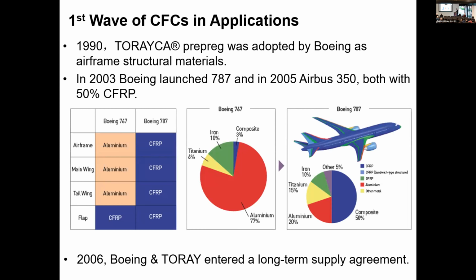If we look here, comparing the 767 and the 787, initially the 767 had a lot of parts in aluminum alloy, and you can see the aluminum alloy is 77% of the whole structure. And then we come to the Boeing 787. The main frame, main wings, and the tail wings are all carbon fiber composite, 50% carbon fiber composite. In 2006, Boeing and Toray came to a long-term supply agreement, so they certainly use carbon fiber as the main material.